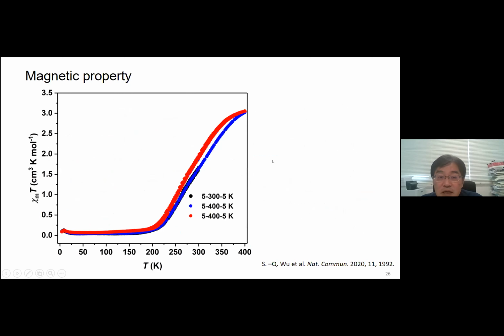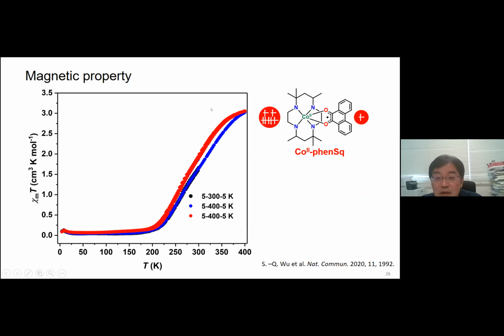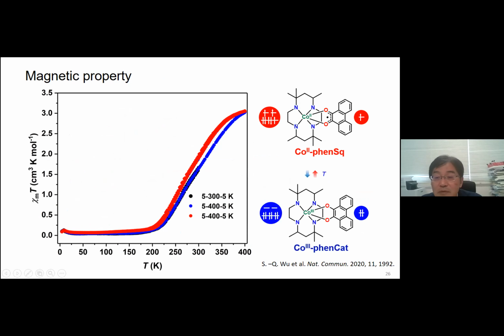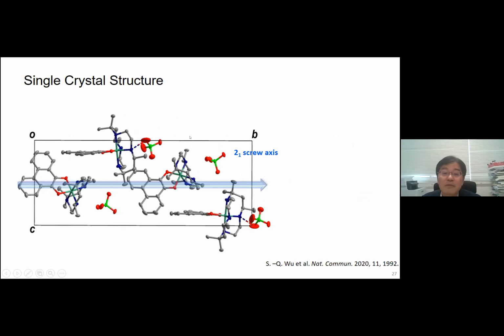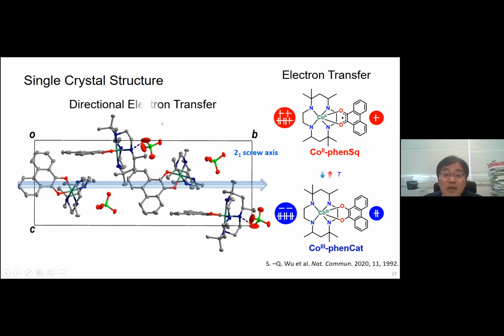And these molecules exhibit valence tautomeric behavior. At high temperature, cobalt-2 high spin state; on cooling, electron transfer is induced, forming the cobalt-3 state. So this is valence tautomeric behavior. The transition is around 300 Kelvin. And as I mentioned, this crystal has a polar structure. So this electron transfer is directional. Electron transfer occurs from ligand to metal, as shown here. So this compound exhibits polarization switching. The origin is electron transfer.